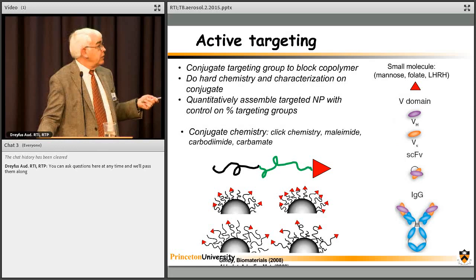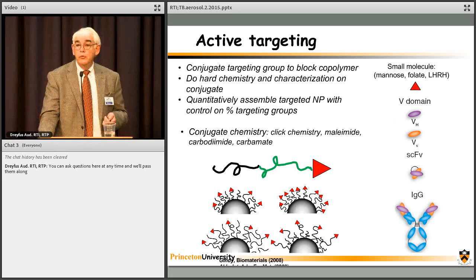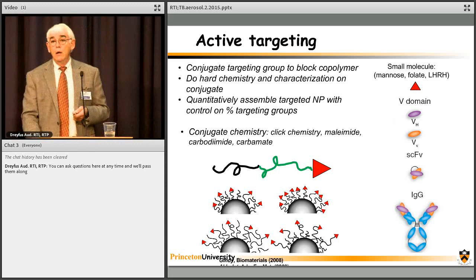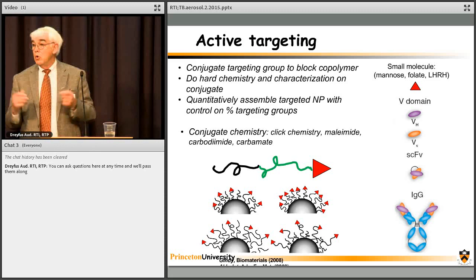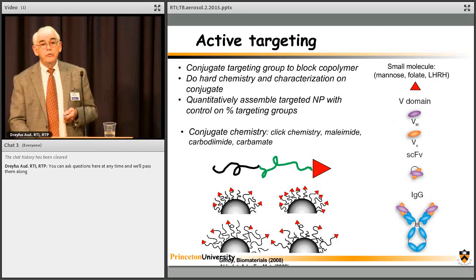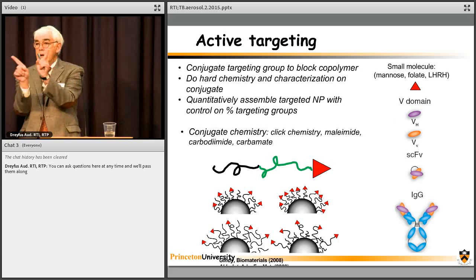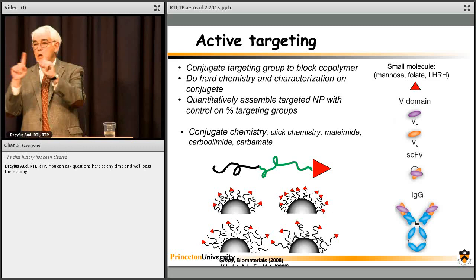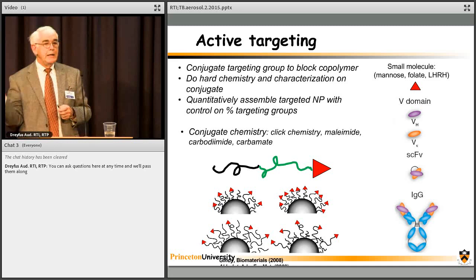And the idea there is that antibodies are extremely expensive to make and difficult to do reproducibly. The single chain fragments, basically the recognition fragment off that antibody, can be made in E. coli at 3 orders of magnitude less cost than making the full antibody. And you have control over it. So if we can put those on the surface of our nanoparticle, the question is, we will never get the same specificity as a full antibody, because a full antibody has the spacing and rigidity. Even if we put these on two chains that have flexibility, that entropy fights against you. So we'd never expect the binding constant to be as good as an antibody, but we actually don't need it to be as good as an antibody. We just need to be good enough. Okay.